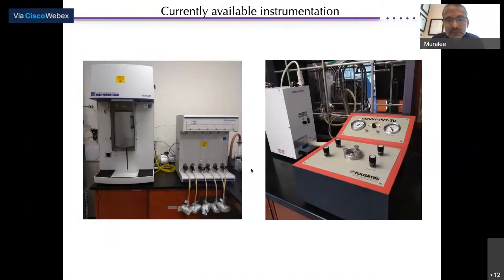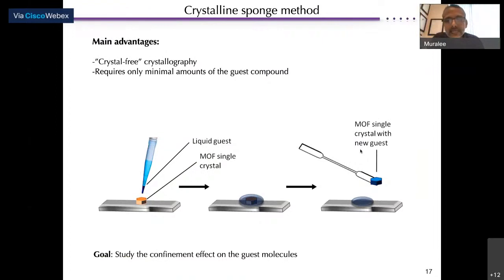So one thing we are currently trying to do is with our new setup, this is a little bit of a promotion for my laboratory. Basically, we have a new Micromeritics setup that we can do gas adsorption, physisorption, as well as chemisorption. Here is a classical activating methodology that we use for this instrument. But if your MOF is highly unstable, we can also use the supercritical CO2 dryer, where you can use solvent exchange using the CO2 dryer, which is a milder condition, which keeps the whole MOF stable in order to do these experiments. So we can do that. In case you are interested in collaborating, send me an email. I'm happy to look into it and help you out.